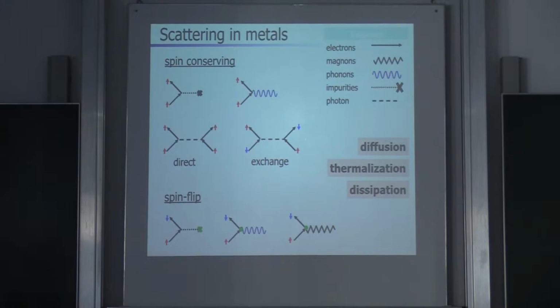But there's also energy exchange with different systems. So there's also thermalization. If we have hot electrons and cold phonons, by the electron-phonon interaction they're able to exchange energy, and depending on how efficient the scattering is, at some point the temperatures will be the same. There's also thermalization between the up and down spin electrons. But these scattering processes do not destroy any spin information. In order to do that, you need spin flip scattering, like magnetic impurities or spin-orbit impurities. There's also spin flip scattering at phonons if you have spin-orbit interaction, and in ferromagnets also with magnons.